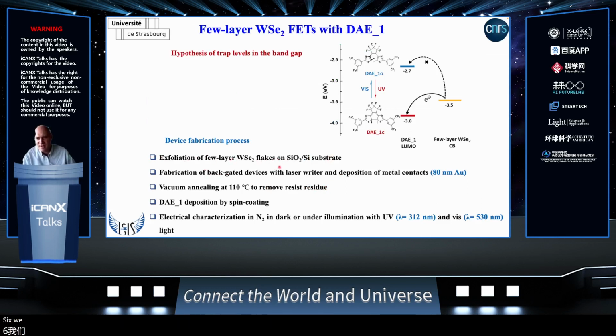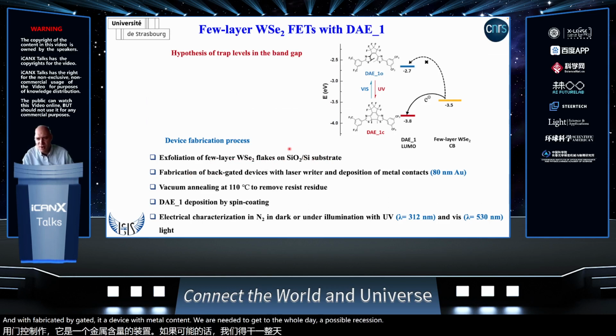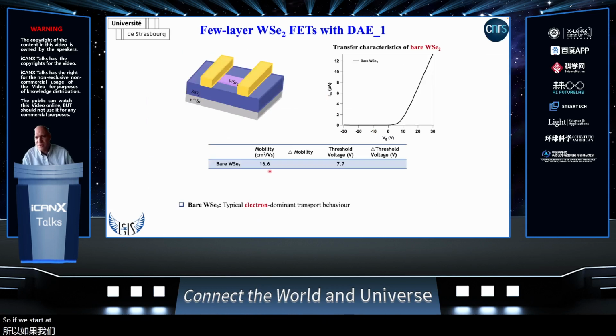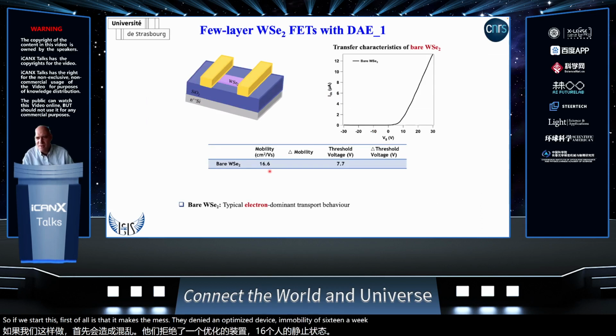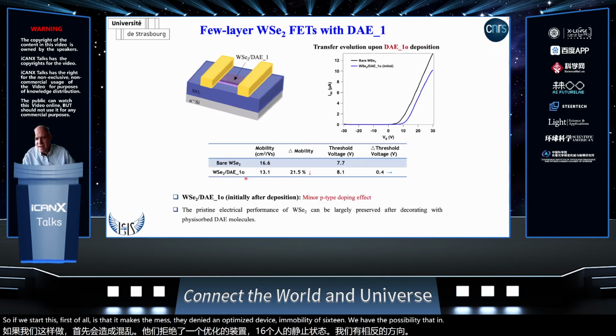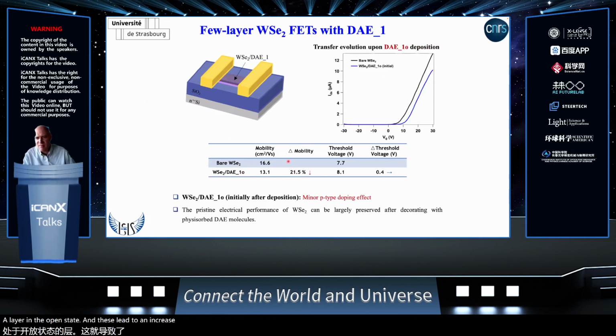We transfer this to the silicon dioxide, and we fabricate a back-gated device with metal contacts. We anneal to get rid of all the possible residue from the patterning, and then we deposit a thin layer of about 5 nanometers of diarylethene by spin coating, and then we perform the characterization under nitrogen upon illumination at different wavelengths. If we start first of all with the tungsten diselenide, an optimized device, a mobility of 16, we have deposited the diarylethene layer in the open state, and this leads to a decrease of 20% of the mobility.